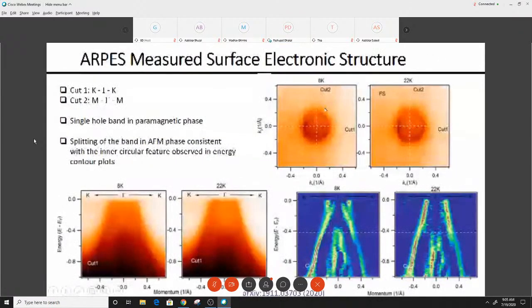Here I present the dispersion maps in the paramagnetic and antiferromagnetic phases, consistent with the features observed in the Fermi surface and energy contours. We can see a single hole band in the paramagnetic phase and the splitting of the hole band in the vicinity of the Fermi level in the antiferromagnetic phase. These features can be more clearly visualized in these second derivative plots, where there is clear band splitting in the antiferromagnetic phase.